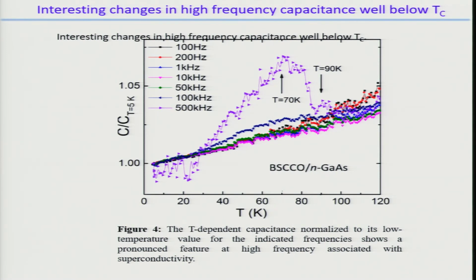In fact, VBI for BSCCO is higher than it is for all of our other materials. So there's something going on at the interface that's causing an additional flat band shift due to the BSCCO, and there's some changes involved at the transition temperature, which may be related to screening lengths, et cetera. And that's not understood, but it's certainly evident in the experiment. It's always fun to show data which you don't understand.